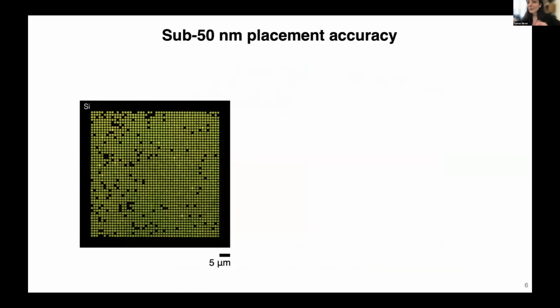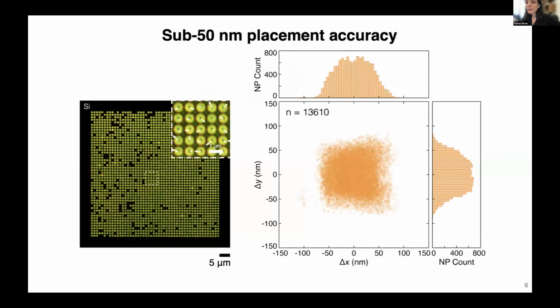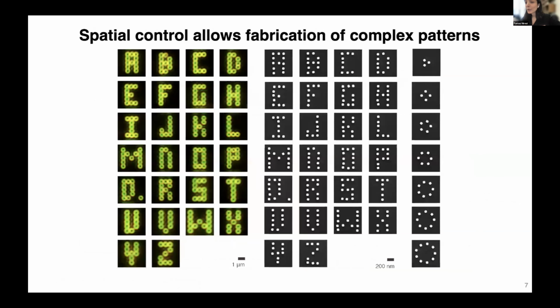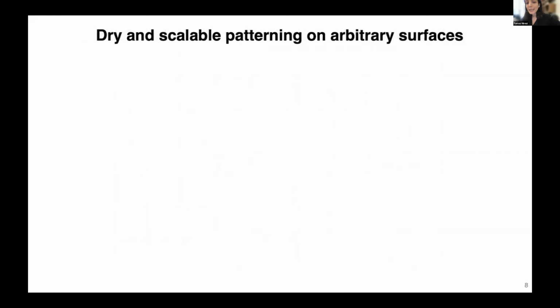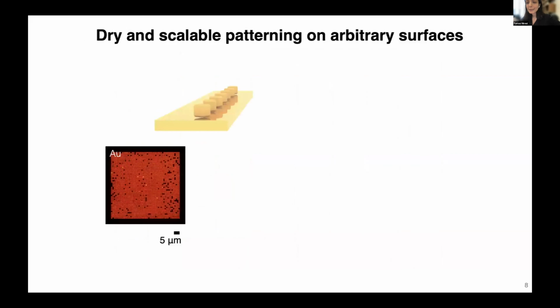And now that we have an array of these particles, we can do high throughput characterization of metrics that are important for process development, for example, placement accuracy. So in this case, we characterized over more than 13,000 particles, with placement accuracy of less than 50 nanometers. As we have control over placement of the nanoparticles, we can also achieve more complex structures and process the nanoparticles onto arbitrary surfaces.